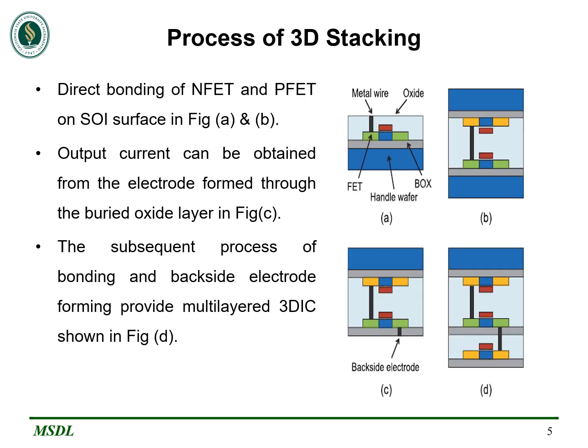In this slide, we are talking about the proposed 3D stacking process by direct wafer bonding. Fully depleted silicon on insulator wafers of NFET and PFET with metal wires are directly bonded on the SOI surface as shown in figure A and B, which is followed by the backside electrode process reported in figure C. Owing to the electrical conductance of fully depleted SOI and minimized interconnect length between the mated FETs, the output current can be obtained from the electrode formed through the buried oxide layer without attenuation. The subsequent process of bonding and backside electrode forming provides the multi-layered 3D IC as shown in figure D.